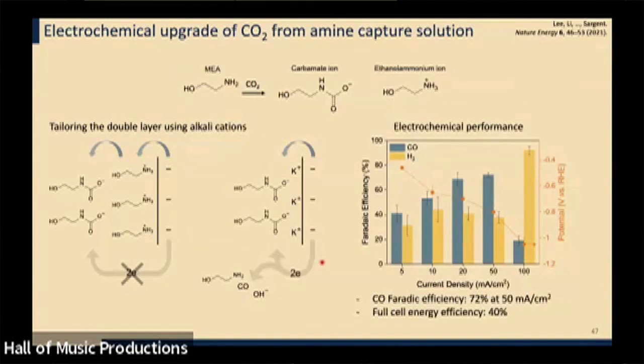And we implemented it first with amines, liquid amines, that are used already in CO2 capture, especially in the flue gas application, and found that when we engineered the electrolyte, we could produce carbon monoxide, which can be then further reacted downstream. We could produce that with a 72% Faraday efficiency in this direct fashion electrically.